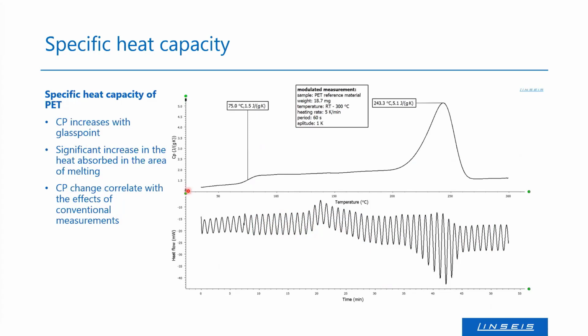So now let's come back to our PET measurement. Here you can find some more information about the measurement and a short evaluation. As I already mentioned, you can find the glass transition at 75 degrees, and also the melting at roughly 243 degrees Celsius. The sample itself was a complete granule with 18.7 milligram, and I measured, as you can see here, from 30 up to 300 degrees Celsius with a heating rate of 5 Kelvin per minute, a period of 60 seconds, and an amplitude of 1 Kelvin.